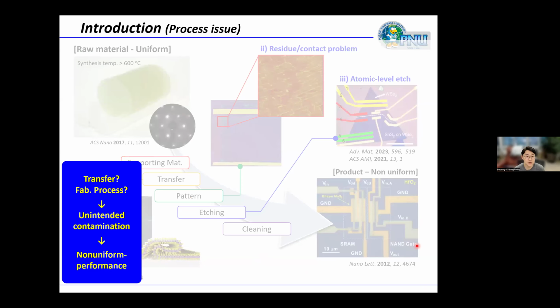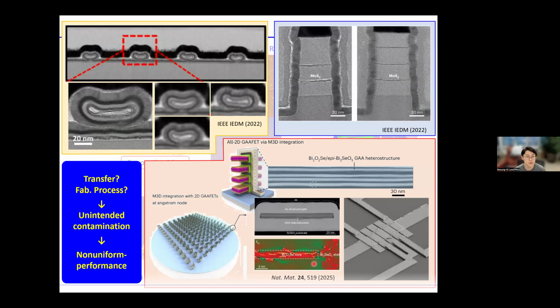So these issues are not limited to a few research groups. Even in well-equipped companies and research institutes, device uniformity also remains a challenge. When you check the reported results, each device often shows variation in its cross-sectional structure. As shown here, when comparing the devices within an array, unintended variation degrades the uniformity of their electrical properties.